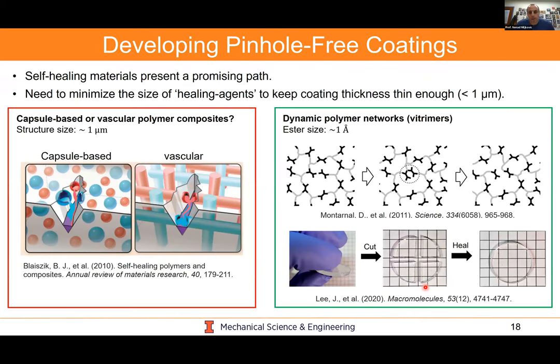And so I'm going to shift my talk a little bit now and discuss three different approaches that we developed using this theoretical framework, this experimentally verified theoretical framework, to develop a subset of coatings which are very, very promising candidates to solve this problem finally. And so the first approach we took was, how do we develop coatings which are pinhole free? Because you may ask yourself, well, if you could remove pinholes completely, you're not going to see any of this happen. And so we looked at previous literature, and one particular idea that we liked was self-healing coatings. And this is actually work which was pioneered here at Illinois by Nancy Sottos and Scott White, as well as others in the chemistry department. Typically, the way these work is a coating where it's encapsulated with what's known as a payload. If you scratch this coating, the actual payload can be released. This can be an epoxy kind of formulation. And the coating itself can heal, and any pinhole that's formed can actually be filled.